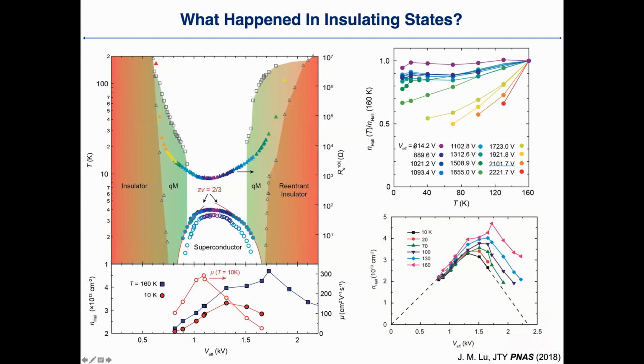One subtle detail is here. Here we have some very, very large electric field that actually corresponds to the translated electric field into the gate capability of the silicon dioxide. So namely, if we apply an ionic liquid gating, the effect is equivalent to like 2,000 volt through the silicon dioxide. And here, as a function of this equivalent gate voltage, you can see that at low gate voltage, it behaves very, very nicely as a capacitor. But at high gate voltage, the carrier density starts to decrease, and the decrease is actually a function of the temperature. At low temperature, the decrease is very significant, and eventually the system becomes insulating.